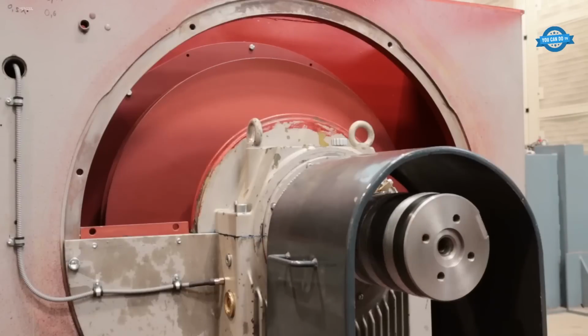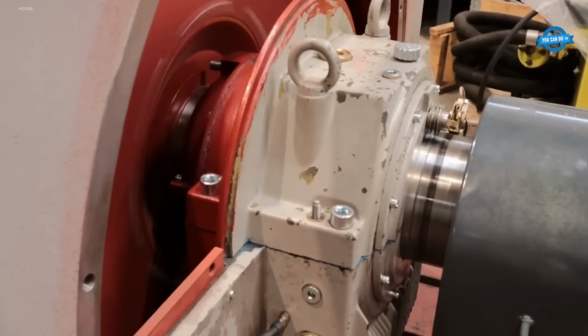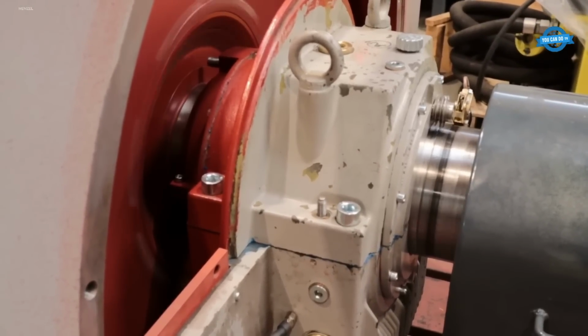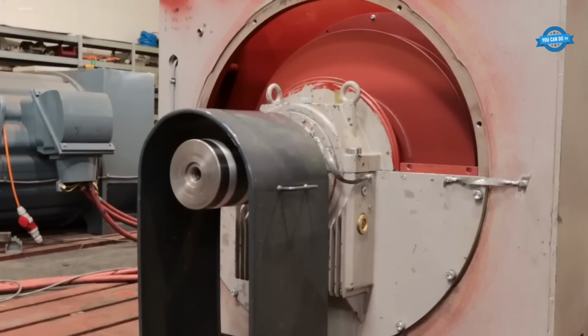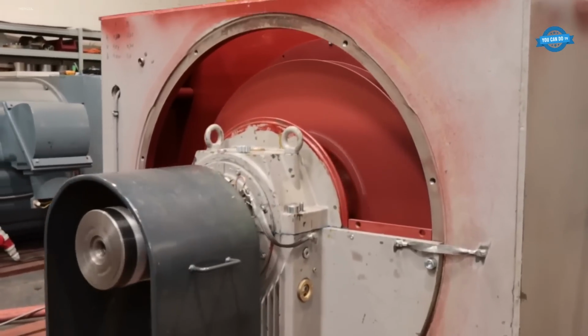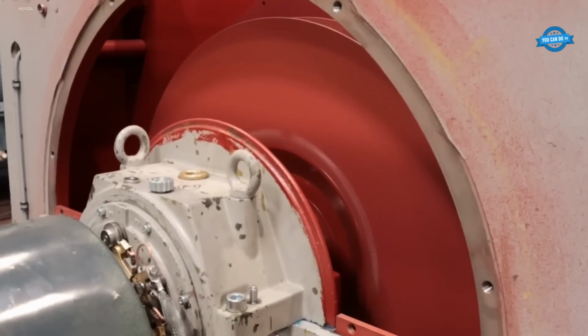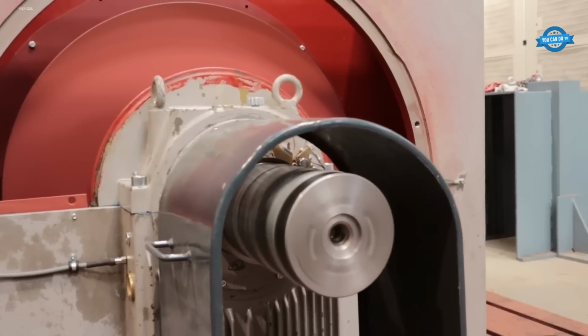This 3,000 kilowatt, 6-pole slip ring motor undergoes a startup test, accelerating from 0 to 993 revolutions per minute in 90 seconds. Operating at 10,500 volts with a shaft height of 630 millimeters and weighing 13.5 tons, it's ideal for cement mills, compressors, and fans requiring high starting torque.